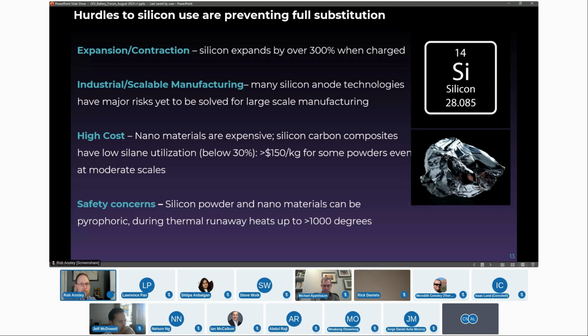But the main issue here is that these structures are very complicated to make. You have to make these carbon cage-like structures impregnated with silane gas. And ultimately, that means that they're over $150 a kilogram. Why is that? Because first you have to make your carbon cage structure, which is pyrolyzing a pitch or some sort of polymer. So you have very low yield from that process. That process alone will lead to about $60 to $80 per kilogram, depending on the purity of the carbon you need. And then the silane gas is $25 to $30 a kilogram.